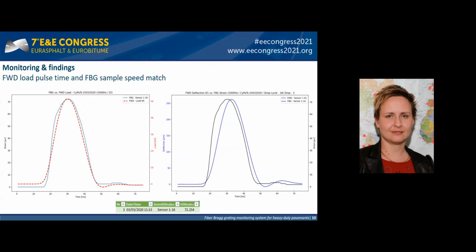Two types of monitoring campaigns were applied: falling weight deflectometer measurements and heavy loaded traffic monitoring. When measuring the pulse time of FWD measurements and matching it with the FBG sensors' response, a very good fit is observed at the high frequencies for signal processing, when the strain value can be clearly extracted from the measurement. The FBG peak shape and pulse time are identical to the falling weight, as you can see here.